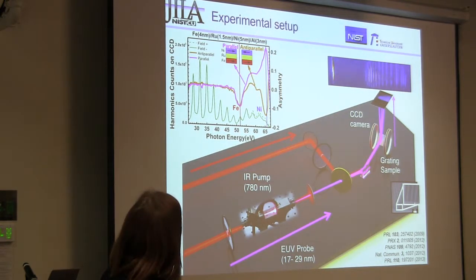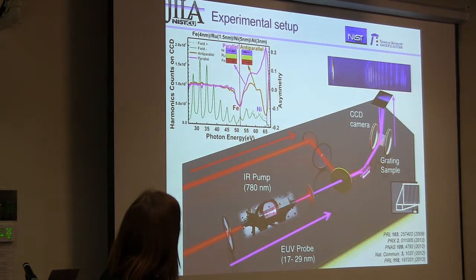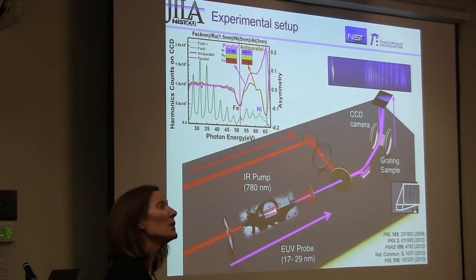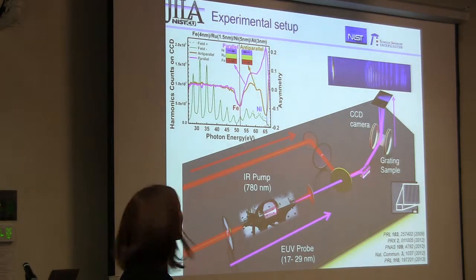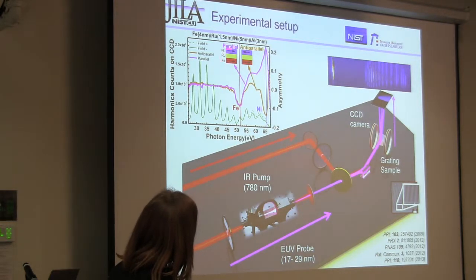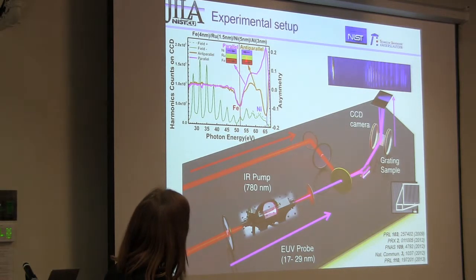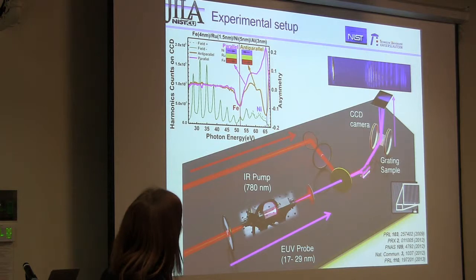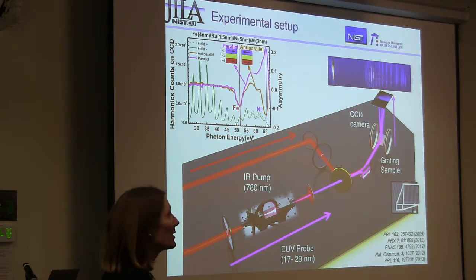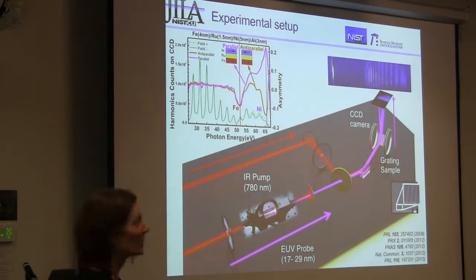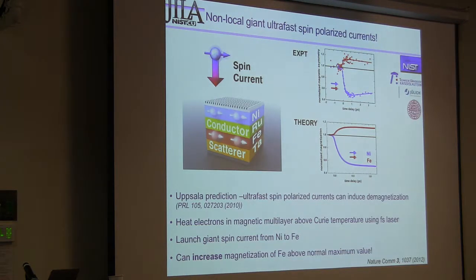And then the nice thing is we can make multilayers with different materials, and if this is about 10 nanometers total, we can still probe down through the different metals, so we can read out the magnetic state. With our NIST colleagues, we can have the two magnetic materials either parallel or anti-parallel, and see if there's a difference in the behavior in both cases. Clearly, if all that was happening was spin scattering, we wouldn't see a lot of difference in these two cases. But if there are spins moving between the layers, we should see a difference if the magnetic moments are aligned parallel or anti-parallel. So that was the experiment.